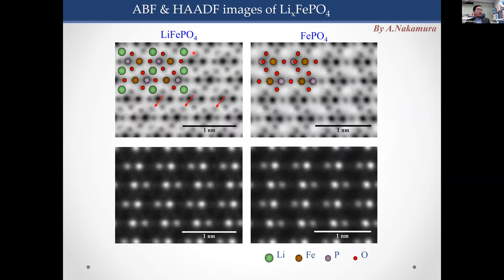And this is a demonstration. This is iron olivine, and this is delithiated olivine. That is, FePO4. This is the ABF image, and the bottom is the HAADF image. In the HAADF image, the framework is not so different, but in the ABF image, you see the lithium columns as indicated by this arrow. After delithiation, that contrast disappears. So this is very powerful to directly see the interface between olivine and delithiated olivine. We applied this technique to characterize this.